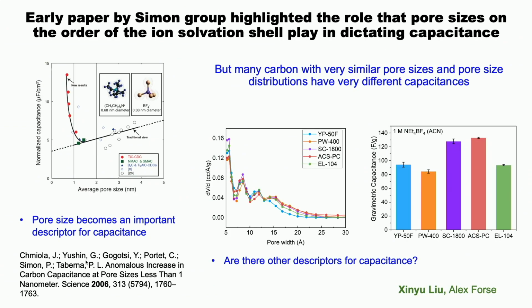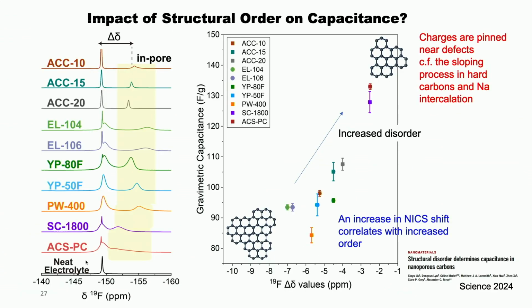And so more recently, we've looked at how to optimize these carbons for these processes. There was a very nice work of Patrice Simon a few years ago that said you wanted pores about the same size of the ions, the solvated ions, and that this was a descriptor for capacitance. Our more recent work with my collaborator Alex Forse showed that actually you could have carbons with very similar pores and you'd have very different capacitances. And actually the better descriptor that we picked out from these NMR signals was the degree of coherence of the carbon sheets. And as the system got more disordered, non-intuitively the capacitance went up.